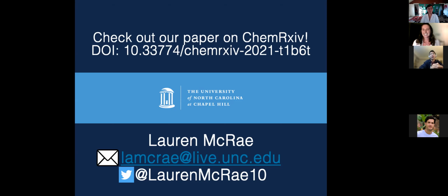You mentioned that you have some defects, which leads to the actual value being far from predicted. Is this defect more referred to the surface defect or any impurity dopant in your semiconductor? It's probably, as I showed from the XRD pattern, we have a 15-ish% of the cubic phase, which does not have the same conductivity as the layered phase. And so that impurity is present in this experimental sample. So I think your second point is right on. We have impurities present in the sample that are affecting the conductivity. Okay, thank you.